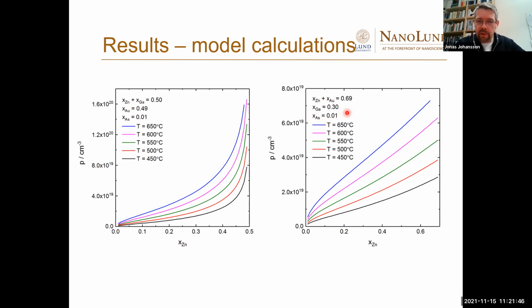Here I have the gallium concentration fixed, and I change the zinc concentration at the expense of the gold concentration instead, also for different temperatures. Here you see that the increase is more linear, but the trend in temperature is the same. So higher temperature, higher doping. And you also see that it's difficult to get low doping. Whatever zinc we put in, the doping concentration tends to be high.